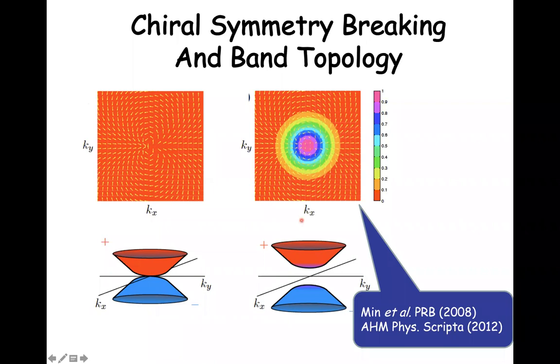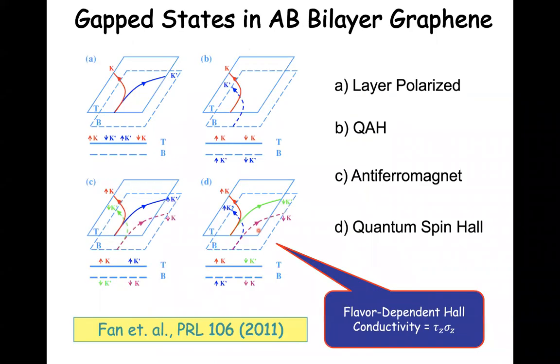And in fact, if we integrate over momentum space, it turns out that the integral is quantized. And through the grace of God, it turns out that this topological characteristic of electronic states, this particular one, is actually something you could measure. It's the Hall effect. So this state with this structure in momentum space gives a non-zero Hall effect, an anomalous Hall effect, a Hall effect without a magnetic field.